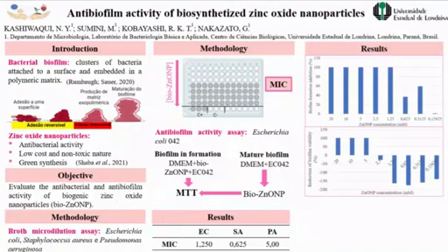The antibiofilm activity assay results are shown in the graphics. It is possible to see that the 5 highest concentrations tested were able to inhibit 100% of the biofilm formation, while the 3 highest concentrations were also able to eliminate the mature biofilm.